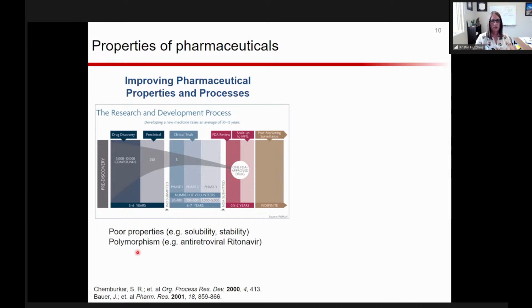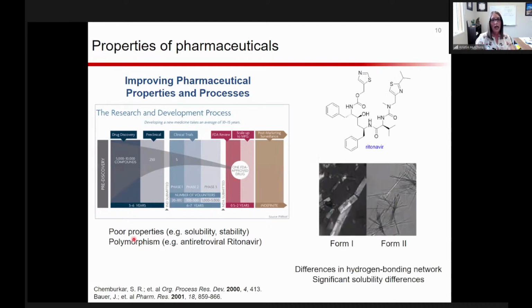Another big issue in pharmaceuticals is polymorphism, meaning that if you have one molecule, it can crystallize into a solid form in multiple different ways. And sometimes those different forms give you different properties. One drug I like to highlight, because it shows a really excellent example, is the antiretroviral ritonavir, which is used for the treatment of AIDS. You can see the structure of ritonavir there, a pretty complicated structure with lots of hydrogen bond donors and acceptors. When ritonavir was being developed, they were only ever able to isolate one polymorph, which is form 1 here.